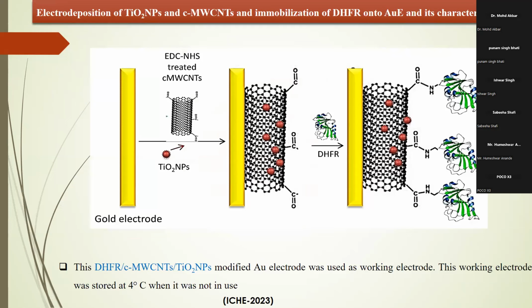Here, the electrodeposition of multi-walled carbon nanotube and the titanium dioxide nanoparticles was done with the help of the 3 electrode system, that is the potentiostat, on the clean gold electrode, and this modified electrode was then dipped into the enzyme buffer containing DHFR, that is dihydrofolate reductase, to immobilize it on the modified electrode. Here the constructed DHFR multi-walled carbon nanotube titanium dioxide nanoparticle modified gold electrode was used as a working electrode. When it was not in use, it was stored at 4 degrees Celsius.